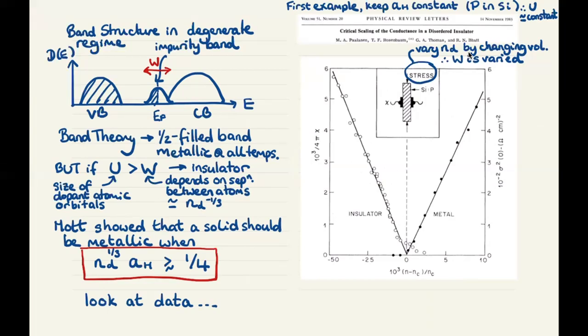So this experiment was done, the silicon was doped with phosphorus. So it was in the degenerate regime. It was a high doping concentration, but it was just on the insulating side of the metal to insulator transition. So it was an insulator and stress was used to increase or decrease the carrier concentration. We should point out that these measurements were done at very low temperature. In fact, this was done below 100 millikelvin because of course at high temperature, the band gap that opens in the impurity band because of correlations is very small and the system just becomes a dirty metal at all temperatures.